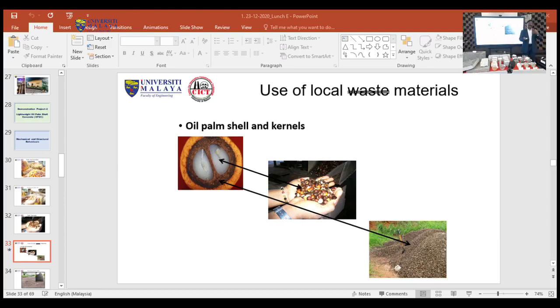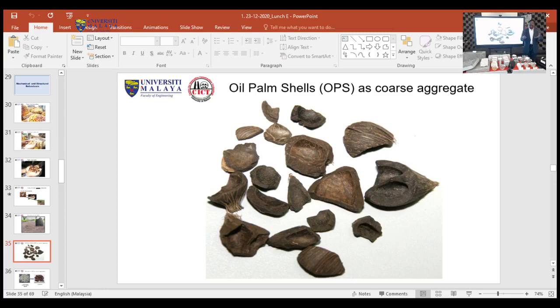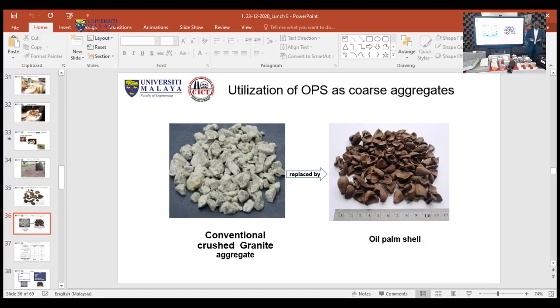So we have collected these shells, and these shells are not like the other coarse aggregates. Hence, we have to investigate the properties, because it has convex and concave surfaces, as you see there. It's not that easy. It could bond with the matrix, cement or other material. It could bond, but it will not be like the other conventional coarse aggregates. So we have investigated, and we have produced normal weight concrete slabs and oil palm shell concrete slabs and beams. First, we investigated the beams. That's what I'm going to show.